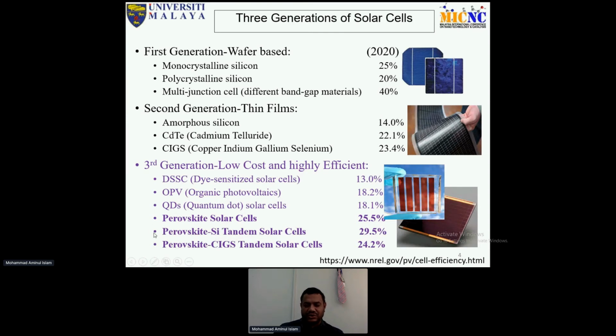But one question is, if the efficiency at lab scale is very, very high, why is it not in the market? The answer is stability. This solar cell is very unstable. Even within 2 days of fabrication it can degrade and lose 100% of its efficiency, because the perovskite material is not stable under humidity, light, even air and oxygen. When it touches air oxygen, it degrades.